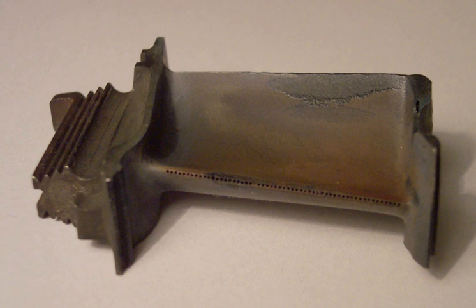At elevated temperature, the free energy associated with the antiphase boundary (APB) is considerably reduced if it lies on a particular plane, which by coincidence is not a permitted slip plane. One set of partial dislocations bounding the APB cross slips so that the APB lies on the low energy plane, and, since this low energy plane is not a permitted slip plane, the dissociated dislocation is now effectively locked.